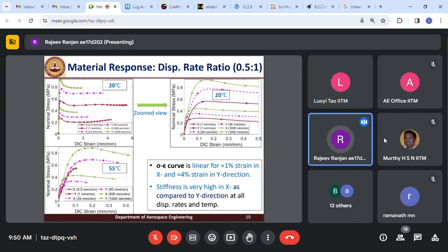Also, it was observed that the stiffness in the x direction is very high as compared to the y direction. Generally, in polymeric or viscoelastic material, as the displacement rate increases, stiffness increases. However, in this case, since the displacement rate is double in the y direction compared to the x direction, that higher displacement rate is causing higher strain in the y direction, and that strain is acting as a pre-strain for the x direction. That is the reason behind higher stiffness in the x direction as compared to the y direction.